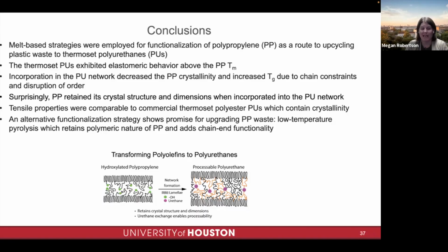In addition, this polymer retained its semi-crystalline nature. Polypropylene essentially crystallized just like polypropylene does, even though it is constrained in this urethane network. We think the amorphous regions contain the urethane crosslinks, which are aggregating, and the crystals are composed of polypropylene, separate from the crosslinks, enabling the polypropylene to crystallize like neat polypropylene, whether we look at the unit cell, the lamellar features, the spherulites, or even the crystallization kinetics. Finally, we looked at one alternative strategy for functionalization, which was using pyrolysis at a lower temperature, which retains more than 90% of the material as a solid with chain-end functionalization that can be useful for further transformations.